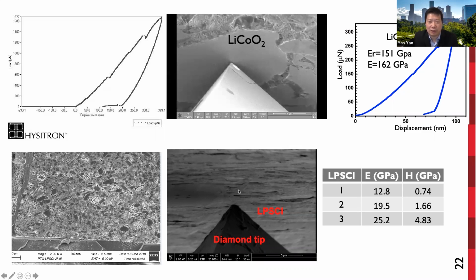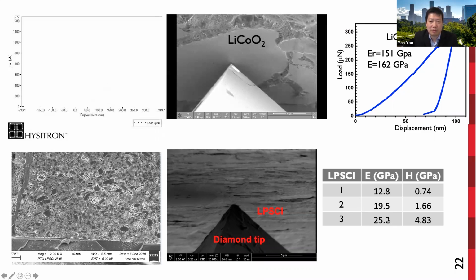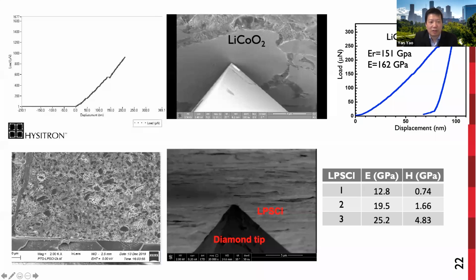If the tip indents the electrolyte area, we will also see the measured modulus of the electrolyte is 1 order of magnitude smaller. So in situ SEM nano-indentation has high spatial resolution to probe the heterogeneous composite cathode, in this case, to differentiate the cathode versus electrolyte, and even to measure the mechanics of the interface.